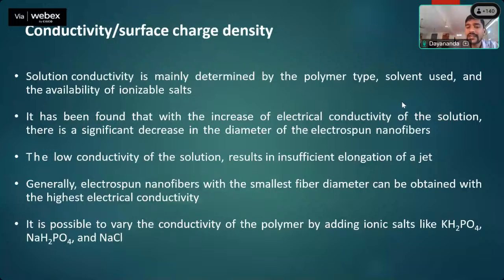It has been found that with an increase in solution conductivity, there is a significant decrease in the diameter of the electrospun nanofiber. With low conductivity, the jet is insufficient - if conductivity is very low, then elongation of the jet during the process becomes extremely difficult. Generally, electrospun nanofiber is obtained with the highest electrical conductivity.